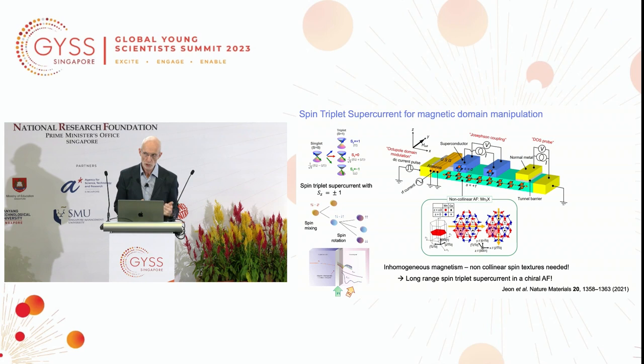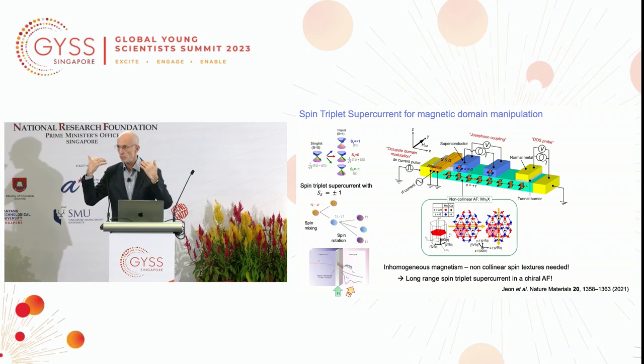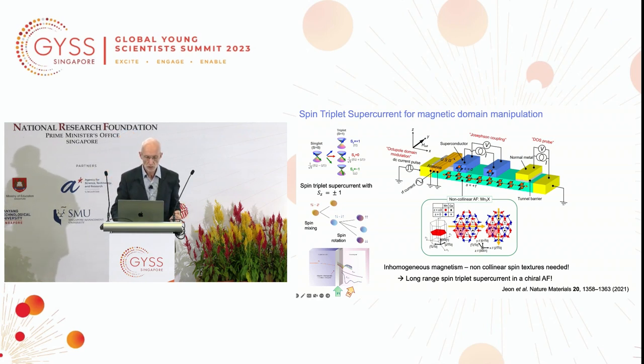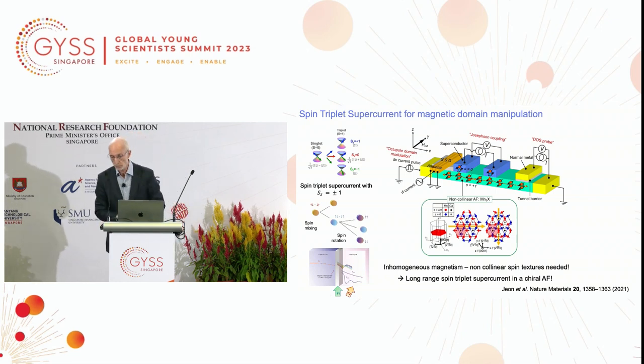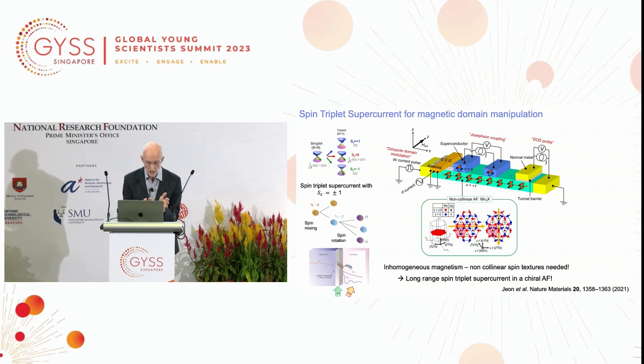textures, we could use one of these to create, by proximity with a conventional superconductor, this is niobium, where the Cooper pairs are formed from antiparallel spin pairs, we could create triplet pairing in this non-collinear spin texture. I don't have detailed time to discuss this, but this is a chiral Kagome antiferromagnet, and we showed the supercurrent could be propagated over long distances.